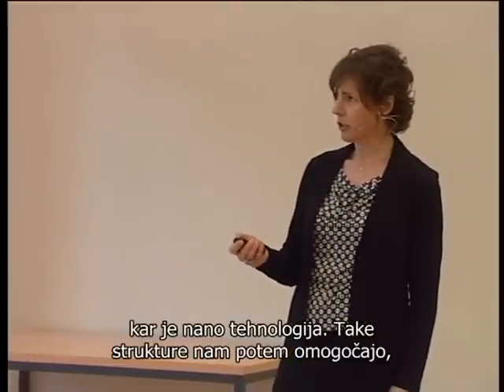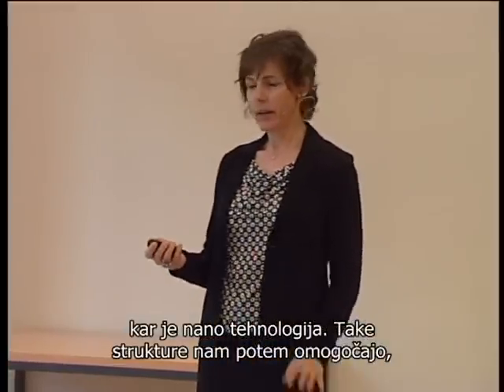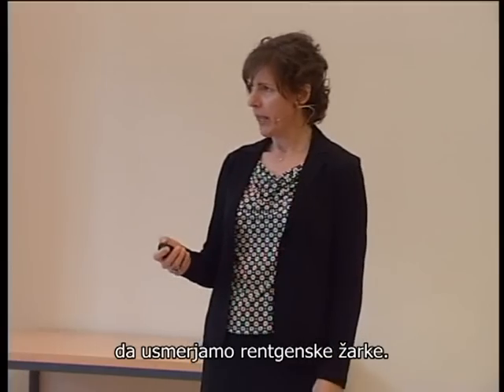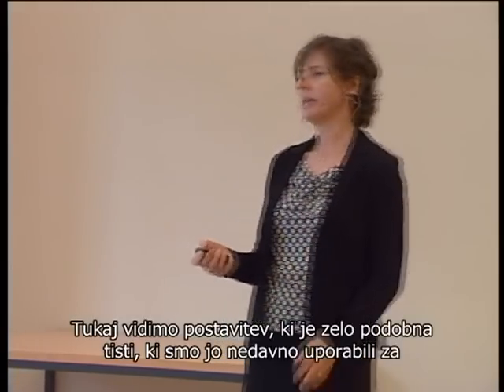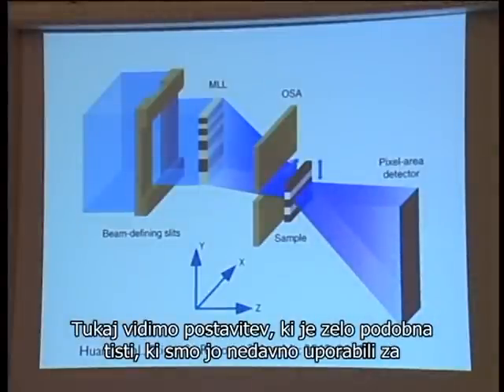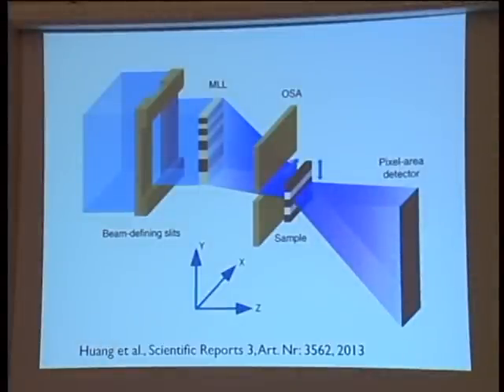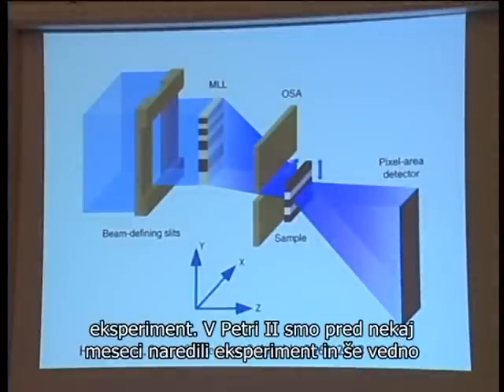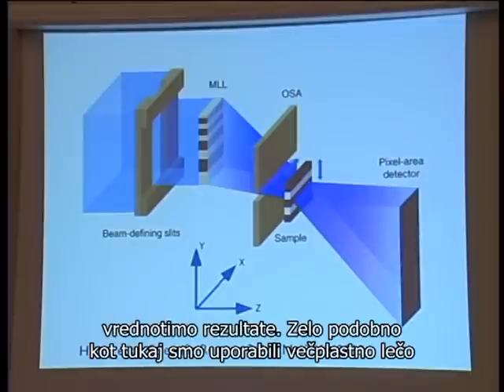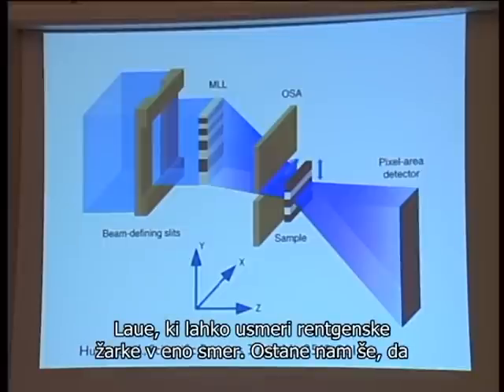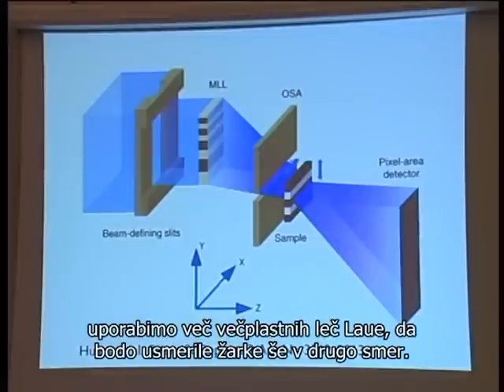So such structures then enable us to focus X-rays, and I'm showing here a setup that is very similar to the one that we used just recently. We did the experiment at PETRA III just a couple of months ago, and we are still evaluating the results. We used a multilayer Laue lens that can focus X-rays in one direction. And of course, we actually have a set of two multilayer Laue lenses, so focusing in the other direction.